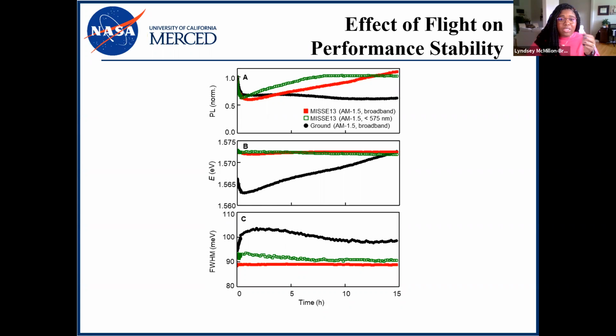In panel A, we see that the ground sample shows an initial fast drop in the PL intensity, and then it stays flat. But conversely, the MISSE13 sample is recovering. We can see that in both the green and the red curves. And actually what we're watching here is the defects in the film forming, but then they're being annealed through light soaking over time. So this is the light-induced healing of strain-induced defects that we're witnessing over this 15-hour experiment.